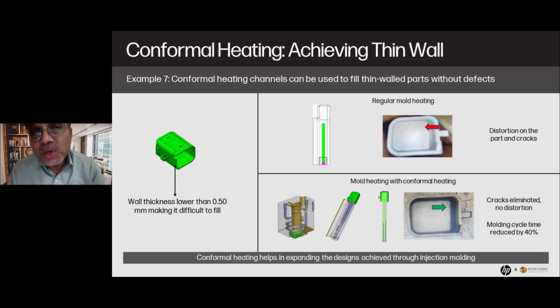Now, that was all about the cooling, but we also noticed that this conformal cooling can also be reversed into a conformal heating. If you look at this component, this is a very small component with a very, very thin wall. And we always struggle to fill the material, because metal injection molding is not like plastic. We are trying to injection mold a semi-solid material. So as the wall thickness reduces, the material loses its heat very, very rapidly. So it's important that, until the last fill point, the mold remains at a particular temperature, and that is only possible if you are able to heat the mold uniformly during part of the filling cycle.